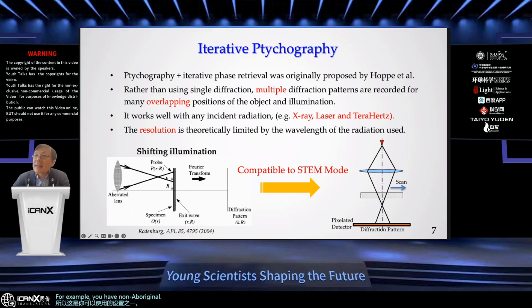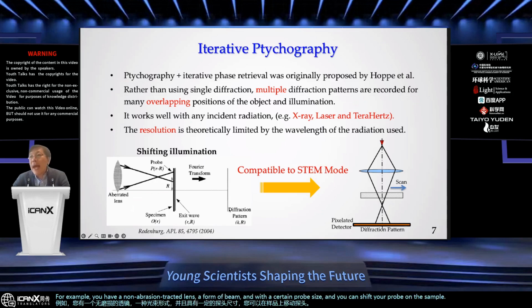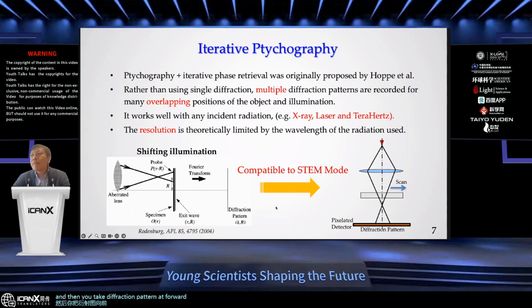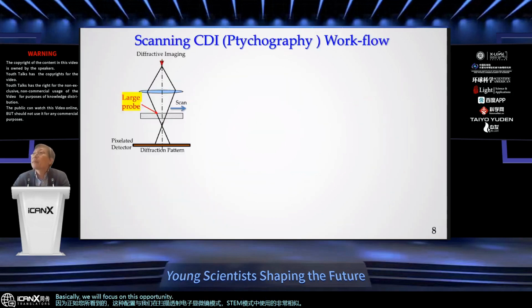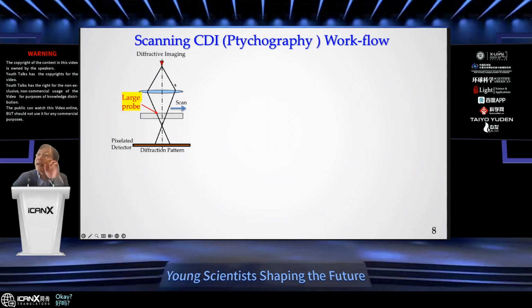non-aberration corrected lens and form a beam with a certain probe size. And you can shift your probe on the sample, and then you take a diffraction pattern in the Fourier domain. Because as you can see, this configuration is very similar to what we use in scanning transmission electron microscopy mode, STEM mode. Therefore, in this talk, basically we will focus on this optical configuration.